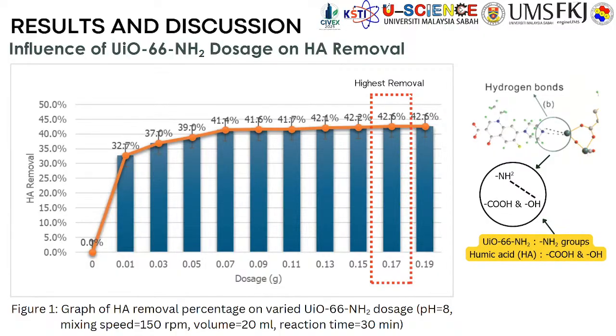Now for this graph, it shows the effects of dosage on HA removal, and we can see that increasing the dosage will also increase the HA removal until it becomes constant at 0.17 gram. This means that the mechanism that happens is hydrogen bonding between NH2 of UiO-66-NH2 and also COOH and OH of humic acid.